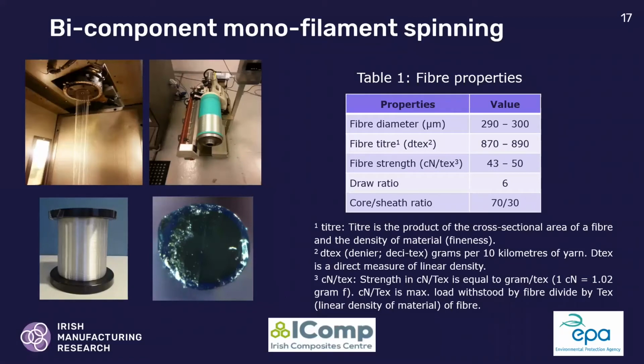The properties are given in the table. The fiber diameter is in microns, 290 to 300, and the fiber titre is in decitex, which is a fineness measure. It's the linear density of the material, which is 870 to 890. And the fiber strength is in centinewton per tex, 43 to 50 centinewton per tex. The centinewton per tex is equal to gram per tex, and this is the maximum load withstood by the fiber divided by the tex of the fiber.